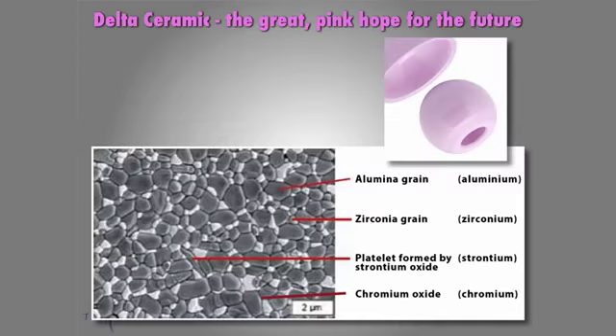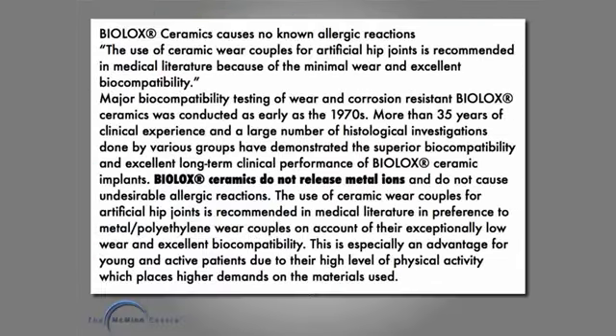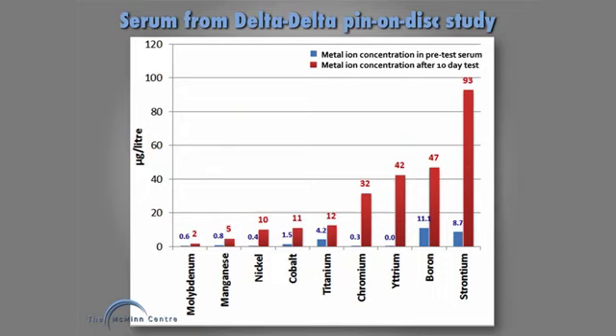Now, Delta is pink because it has chromium in it, and the metals that are advertised to be added to this ceramic are strontium oxide and chromium oxide. And the literature says Biolox ceramics do not release metal ions. Here's the metal ions that the Delta-Delta articulation generates. This is a 10-day Delta-Delta pin-on-disc study, and this was done for me by the laboratory at Smith & Nephew, Memphis. And the blue is the metal ion concentration in the pre-test serum, and the red is the metal ion concentration in the serum after 10 days of running the pin and disc test. And you can see there that chromium goes up 100 times and strontium goes up about 10 times, and a few other metals go up as well.